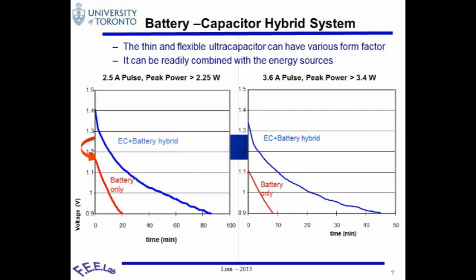However, even with this very thin, flexible device, which only has about 25 millifarads as a device, what you see is the hybrid shows a much longer cycle life. Actually, it died at about 84 to 85 minutes. So the ratio of this with and without is about 4 times more in terms of the energy delivery.